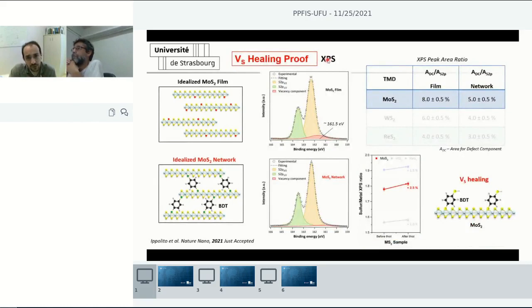But we do see differences from X-ray photoelectron spectroscopy analysis. Here we have the typical sulfur spectrum for the film, where you have the typical peaks for sulfur, and this broader peak or shoulder here accounts for the defects, around 161.5 electron volts. And by doing the functionalization with BDT, this peak here disappears or is reduced significantly. If we do the ratio between the areas of the peaks, we see that there is a decrease of this contribution from 8% to 5% when we use the molecules.